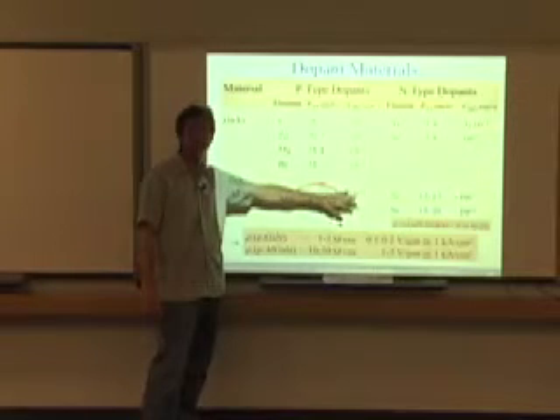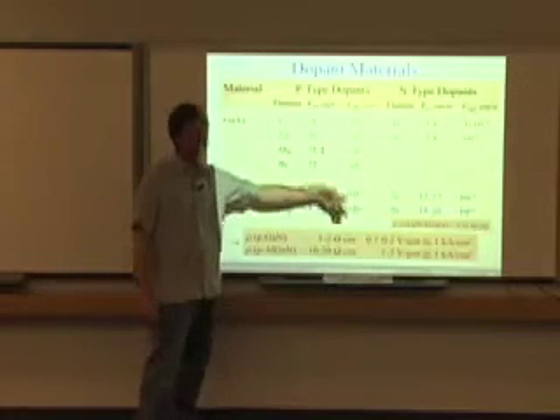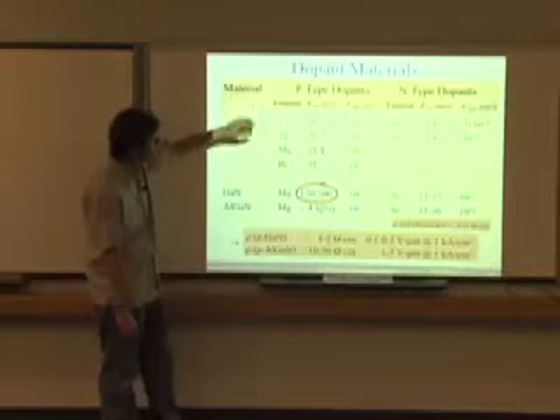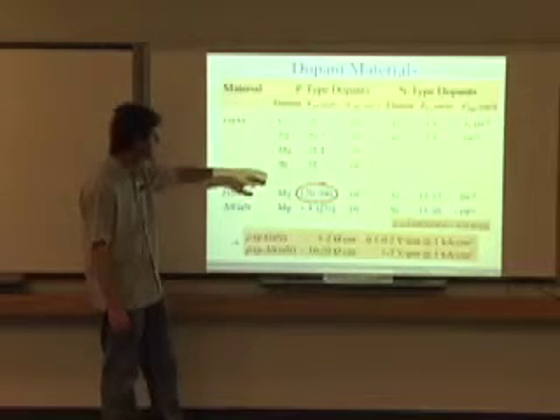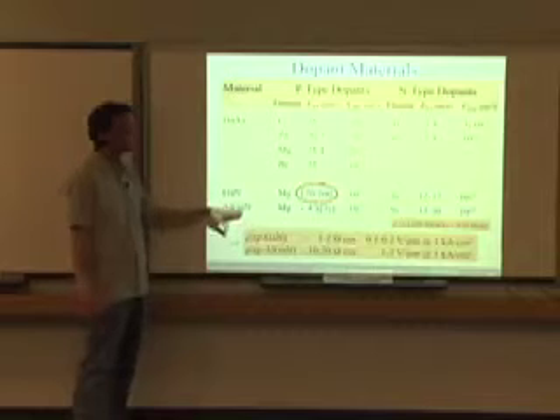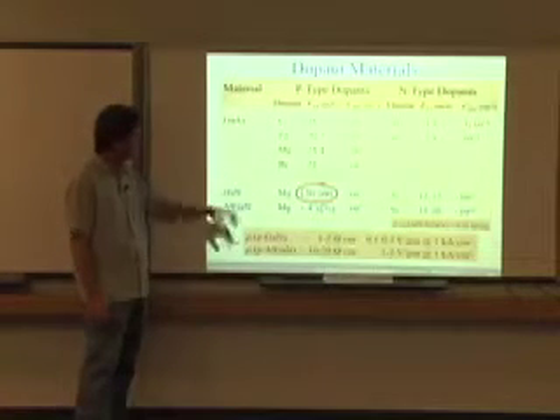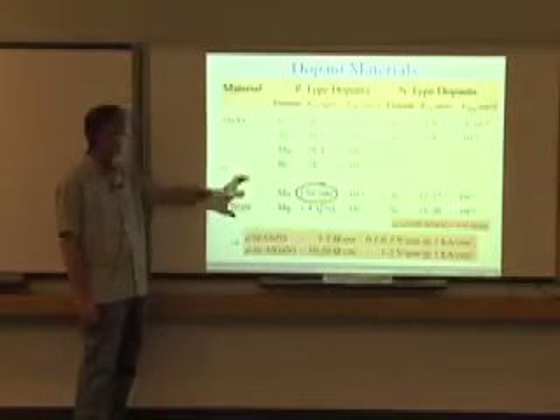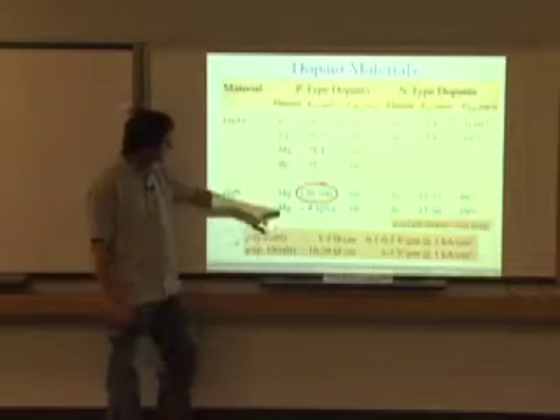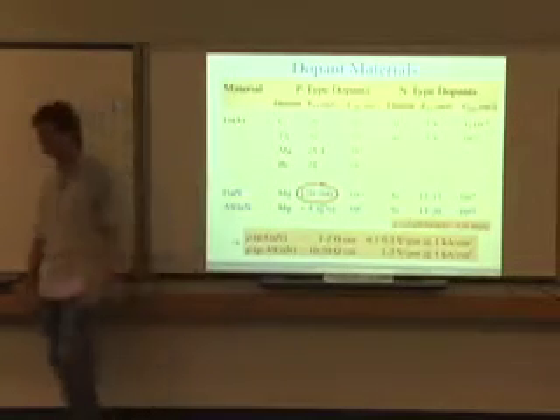The max concentration levels were not that high, especially when you're considering that you need to get to 10 to the 19th for transparency. And the news gets worse as you go to the cladding layers, where you really want your P contact or your P layer to be highly doped. It just gets worse, the activation energy. So it became more of a problem as you went into your cladding layers.